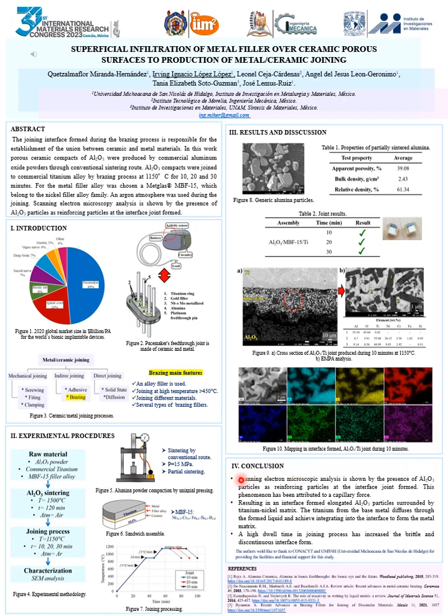Conclusions. The joint was made with ceramic compacts that have a relative density of 61%. Joints at 1150 degrees were possible at different joint times. After 20 minutes of the brazing process, the interface's uniformity is lost. Scanning electron microscopic analysis shows the presence of aluminum oxide particles as reinforcing particles at the interface joint formed. This phenomenon has been attributed to capillary force.